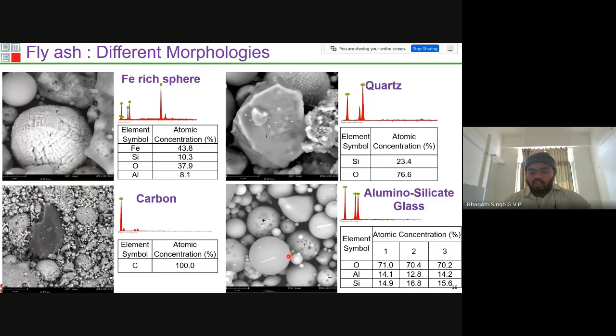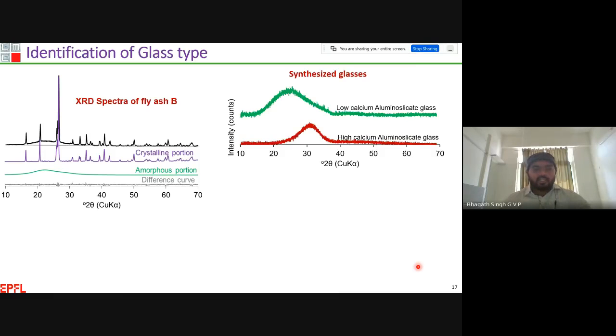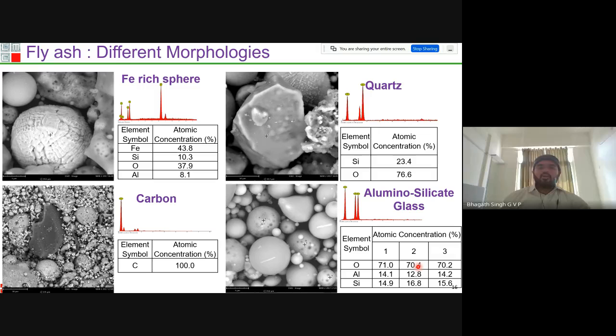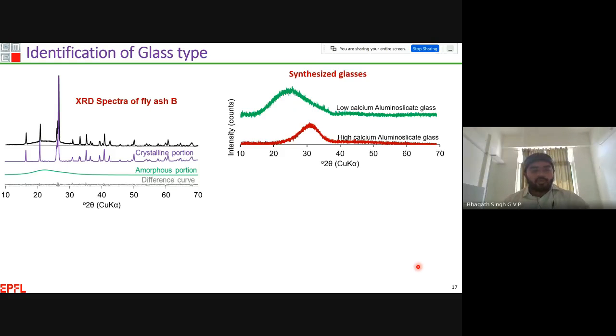And I have carried out EDX analysis on these spheres, and all these spheres are rich in silica as well as alumina. Finally, I have classified these particles as alumina silicate glass. And once I had identified the various morphologies, the reactive and non-reactive potential, and the total amorphous content, then I went one step forward.